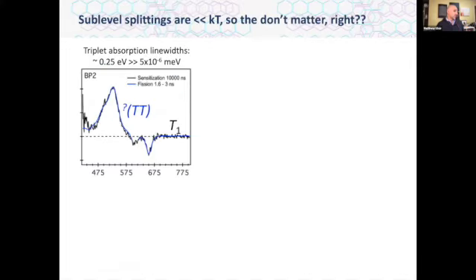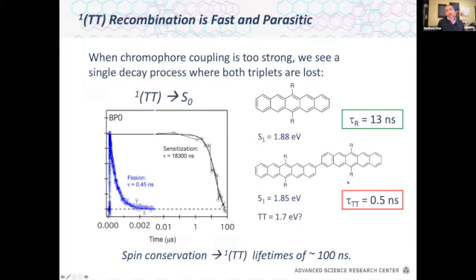1TT. Yeah, this is all non-radiative decay. It's a radiationless, very fast radiationless decay process back to the ground state. This paper isn't out yet, but the group of Nandini and Nath at Cornell has done some really nice theory showing how 1TT can efficiently couple to basically a hot ground state, a vibronically hot ground state. So basically, you've just enhanced the non-radiative decay in this molecule. So for the 1TT, it's super important. When you can conserve spin to get back to the ground state, it's extremely important.